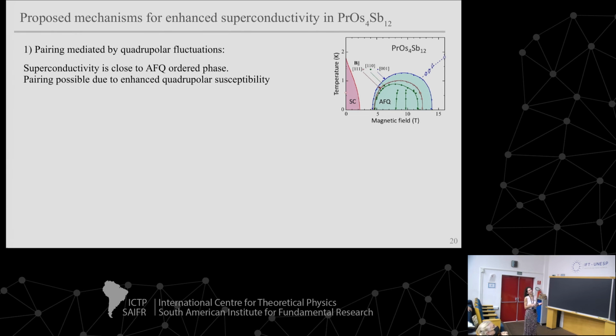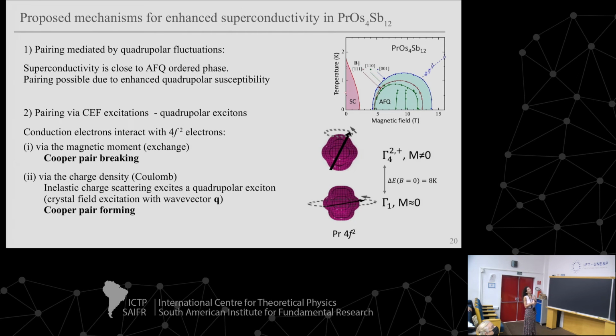So the enhancement or the stabilization of the AFQ phase at lower field would predict enhanced superconductivity, which is not what we see. So this phase is discounted, I think. The other sort of strong proposal is that the extra pairing or the enhanced superconductivity is through crystal field excitations. So in this case, it's a quadrupolar exciton. This is an excitation that develops between the two crystal field levels. The quadrupole exciton is basically just a crystal field excitation that's dispersive with some finite Q.